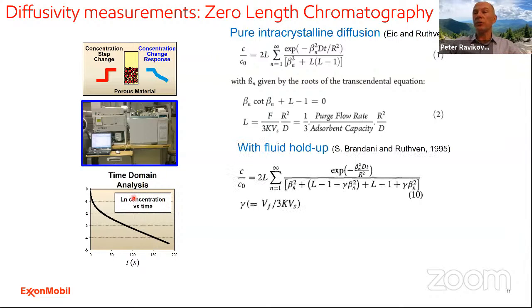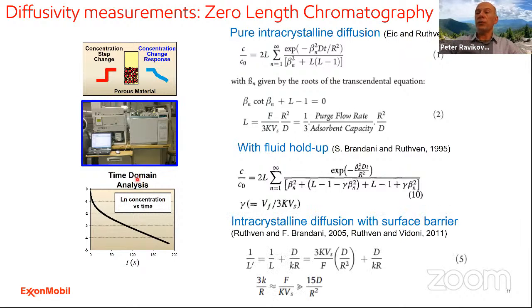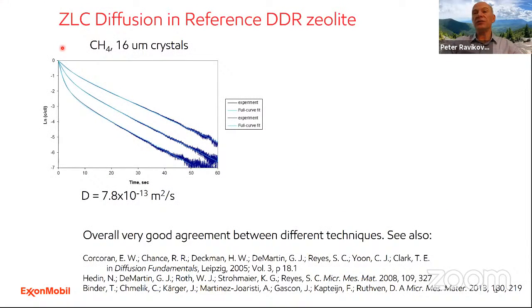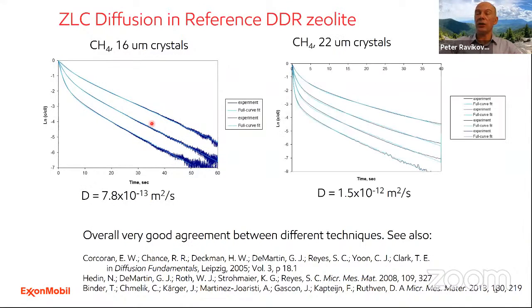There are different models applicable to do this, for pure crystalline diffusion, or when you have a substantial volume of fluid adsorbed versus non-adsorbed, as well as if you have surface barriers. So this is a typical example of methane ZLC curves performed at different flow rate conditions. So you have this typical pattern of parallel curves at different flow rates, and you can extract the diffusion coefficient, which is on the order of 10⁻¹² meters squared per second. You can cross-check it by using different crystals, and the diffusion times will depend as a square of the crystal size. So it's a very sensitive method to double check with a different crystal, and we're getting essentially the same diffusivity. And this diffusivity corresponds to intracrystalline diffusivities.